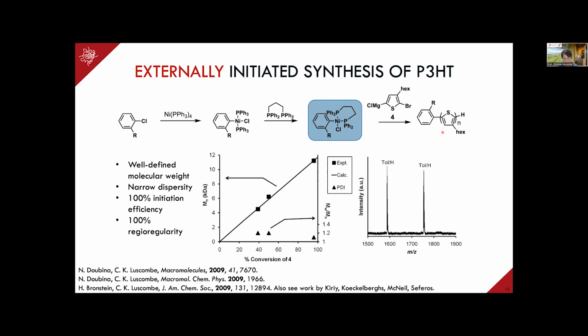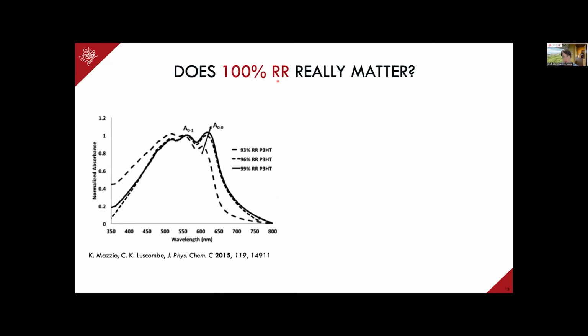So just looking at some brief property aspects of the polymers that we're able to synthesize. So I mentioned that, well, we can make 100% regioregular polymer. And quite often we get asked, well, isn't 98% good enough or 96% good enough? And what we were able to show in an older study here is that actually it does matter, in that by synthesizing a material with greater regioregularity, even if the regioregularity difference is low, we do obtain a more crystalline system.